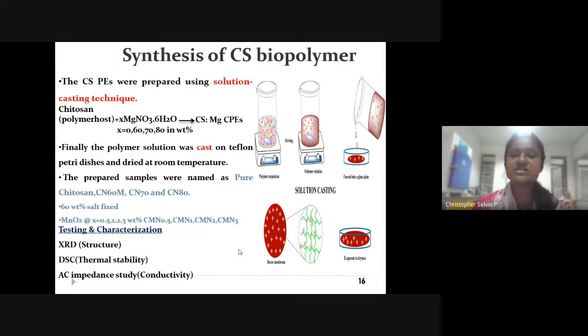So this is the synthesis procedure of chitosan polymer electrolytes. They were prepared using a solution casting technique. A certain amount of chitosan polymer is taken, to which different weight percentages of the magnesium salt are added, and the solutions are stirred until they achieve homogeneity, and then finally cast on Teflon petri dishes and dried at room temperature.